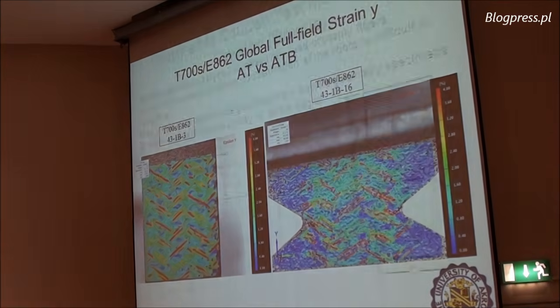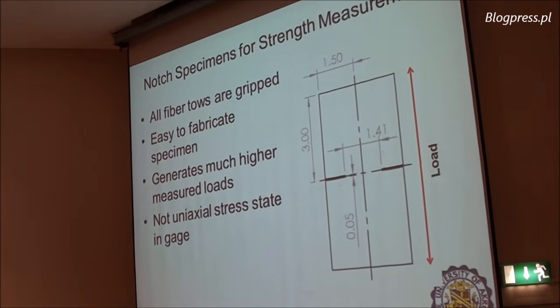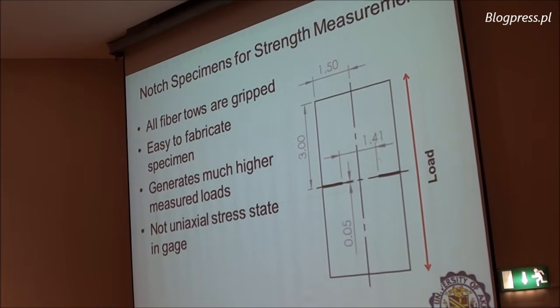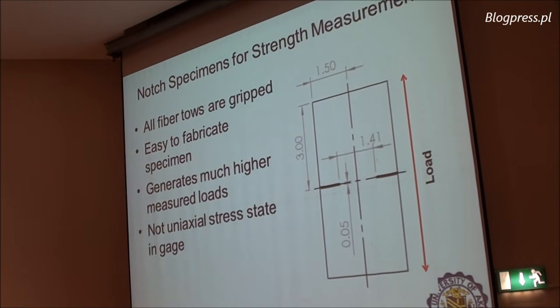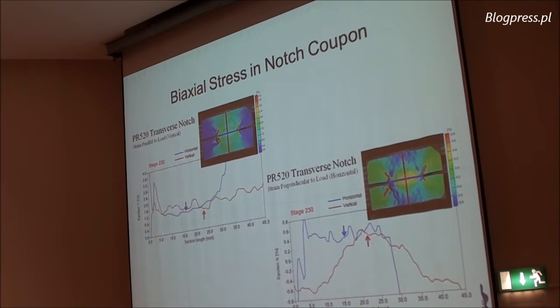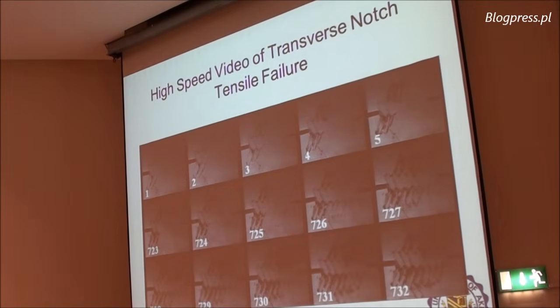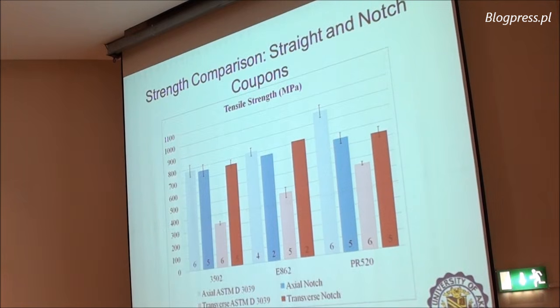for the micromechanical tests. These are tons of tests, so I'm not going to spend too much time. We developed a modified tensile specimen with two slots here, and the idea is that those bundles that come through the gauge area of the test will be embedded in the rest of the material, therefore you will not create those edge effects, and therefore get results closer to the test. However, we found that this has a consequence of testing locally under biaxial loading conditions, not uniaxial, which makes a big difference. And again, high-speed cameras at 100 frames per second can capture the test. It slows down the process of damage because you have these embedded angle fibers, so therefore you can capture that as well pretty good.